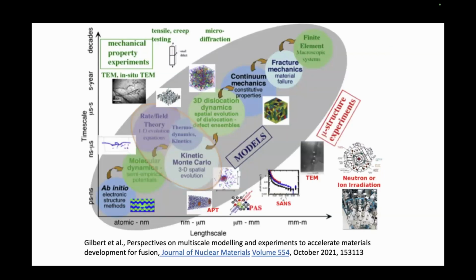So mostly the interaction between hydrogen and dislocation is responsible for hydrogen embrittlement. So we need to really understand the atomistic origin of hydrogen embrittlement. Therefore, we need to go deep into the microscale. You can do some crystal plasticity or phase fields, and mostly we do discrete dislocation dynamics. And two of the most vital inputs for discrete dislocation dynamics are the mobility law and the stress equation.